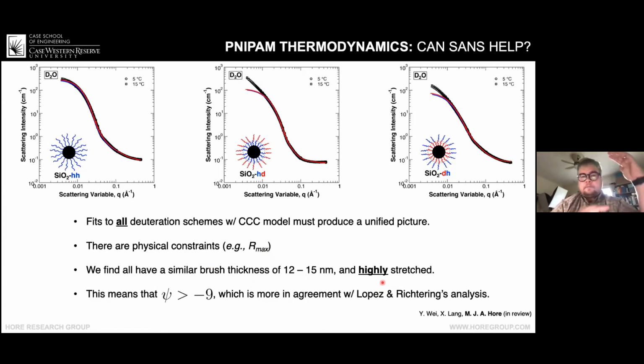And what we mean by highly stretched is that, or I should say more strongly, the end-to-end distance scales as the degree of polymerization to the 0.8 power. So these polymer chains are behaving as if they're entirely in the concentrated polymer brush region. So this means that that parameter psi has to be greater than -9, which is closer to what Lopez and Richtering's analysis provided, which is that it's -2. So we find a value that's closer to the second analysis than it is to the value that's commonly reported in the literature.